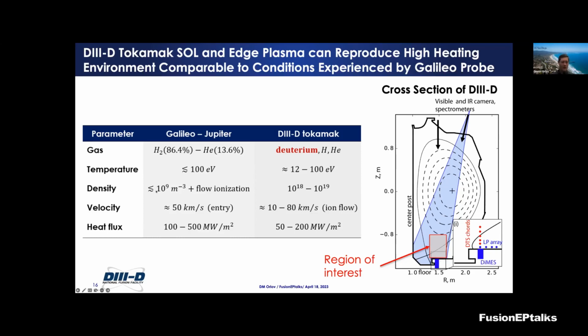The typical densities on Jupiter are 10 to the 9th per meter cubed. That's a lot lower than the DIII-D densities, but you should remember that the density is a lot higher in front of the descending probe. And we've seen the simulation results for the Galileo entry, where the density of the plasma in front of the probe was almost getting close to the numbers that we have in the DIII-D tokamak.